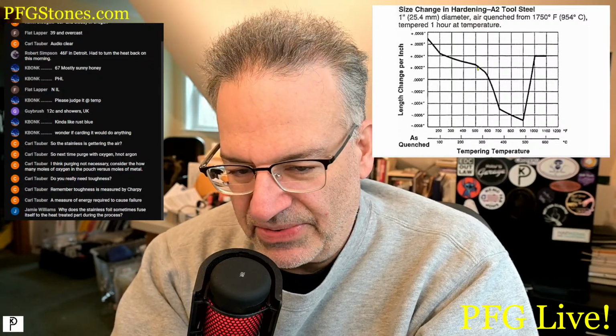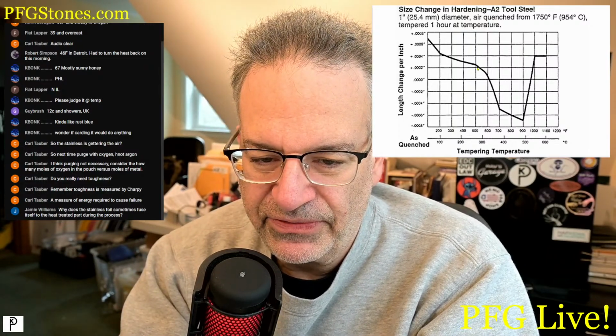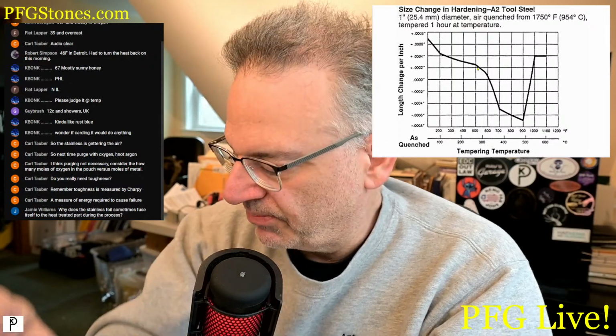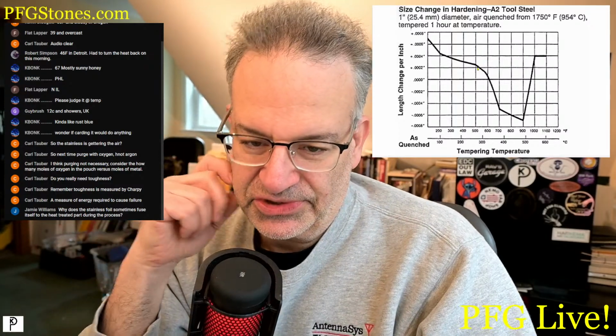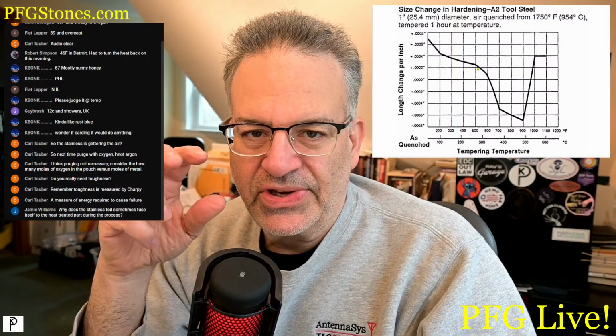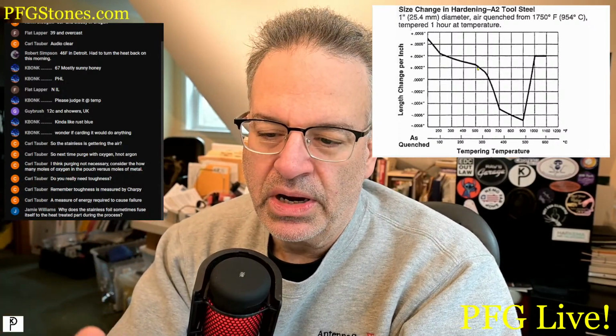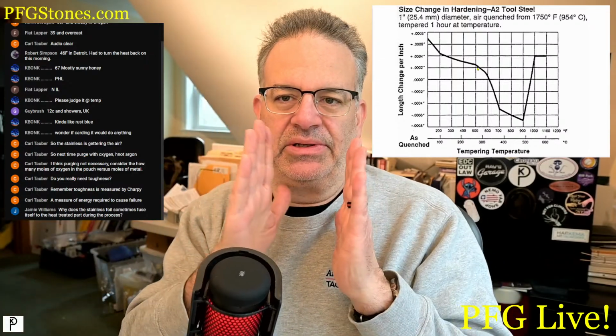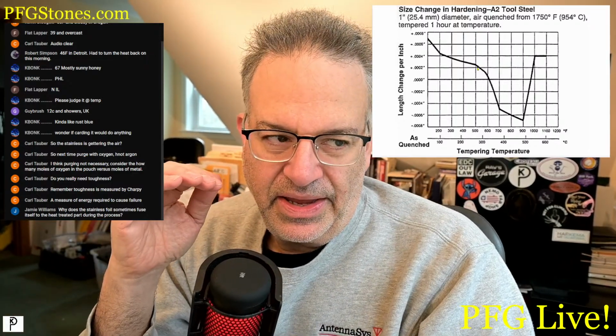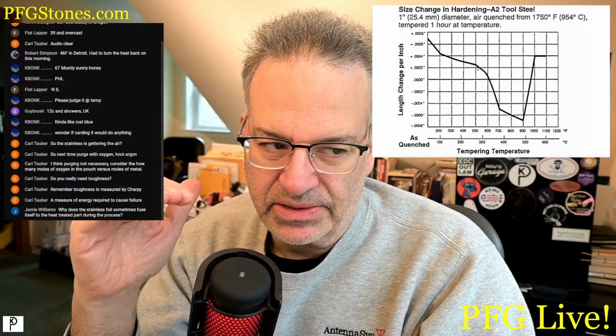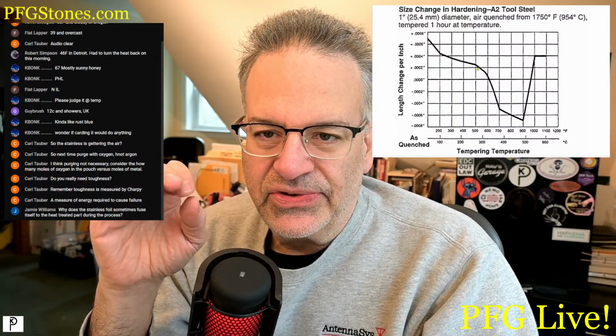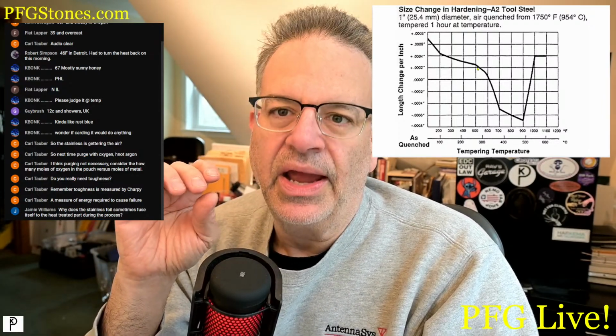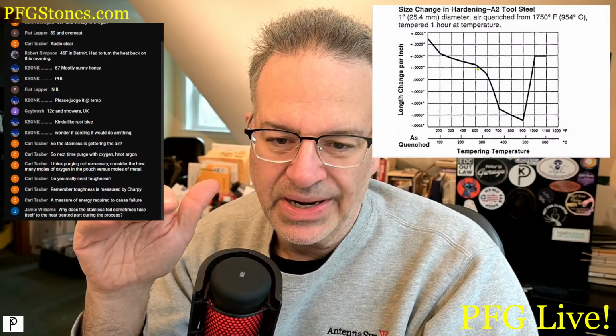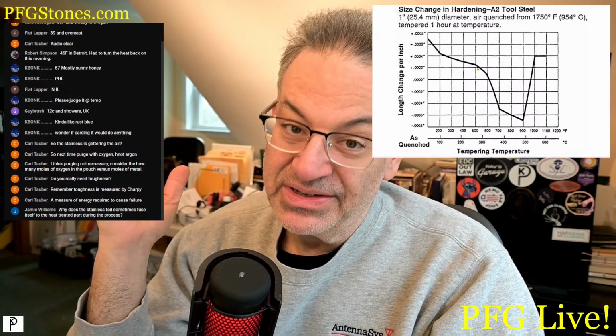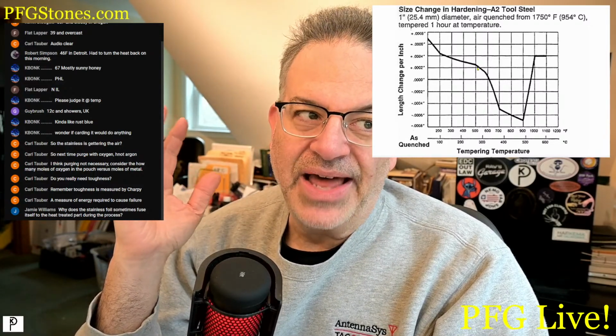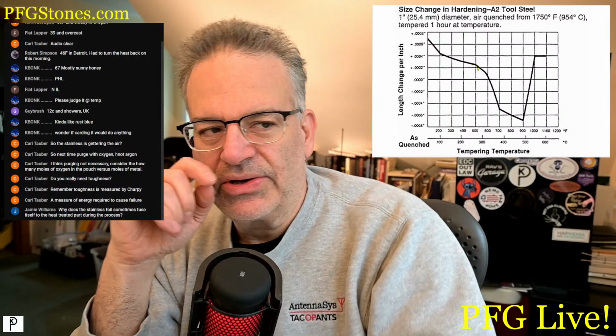Jamie Williams asks a magnificent question. Why does the stainless foil sometimes fuse itself to the heat-treated part during the process? I know half the answer to that question, Jamie. The process of this vacuum packing, right, where the oxygen gets scavenged and the bag literally sucks itself down to the part, puts it in very, very tight proximity to the part. Why there is this fusion between the 309 stainless and your A2 steel or your knife steel part, I'm not exactly sure. But you're at these elevated temperatures. It's not very surprising.